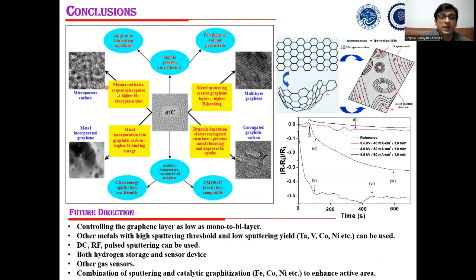On the other hand, the sputtering process is creating microporous carbon. Sputtering is also creating this highly ordered graphene network, and some local curvature, which is improving the hydrogen storage capability. The metal-incorporated graphene is also increasing the hydrogen binding energy. And this is the schematic of the formation of this physisorption material, metal-incorporated graphitic microporous carbon, showing very high hydrogen uptake capability.